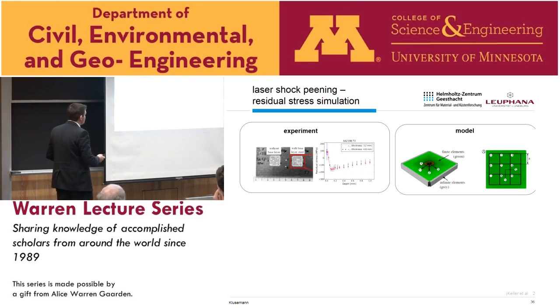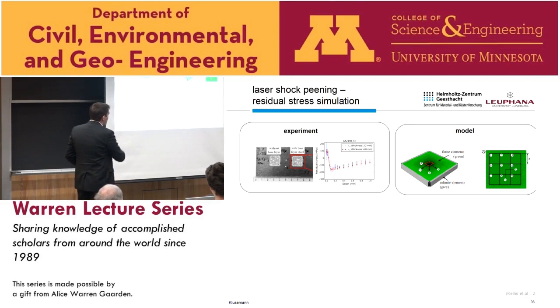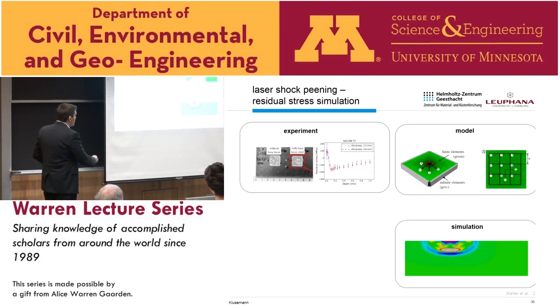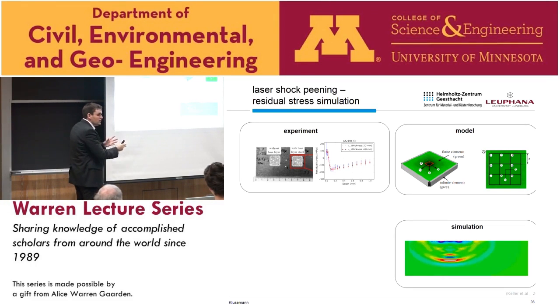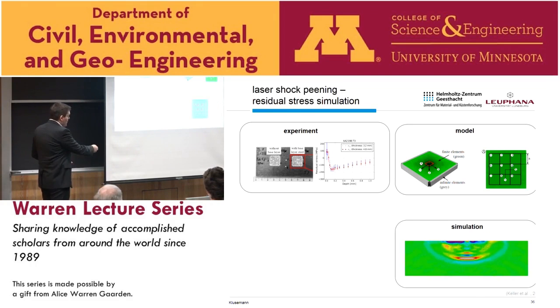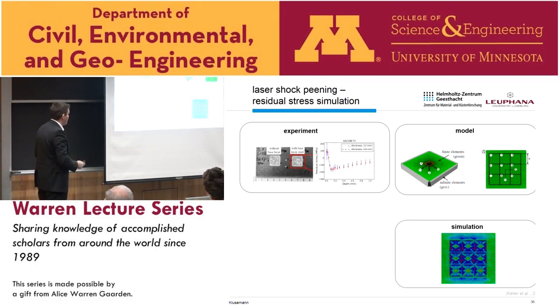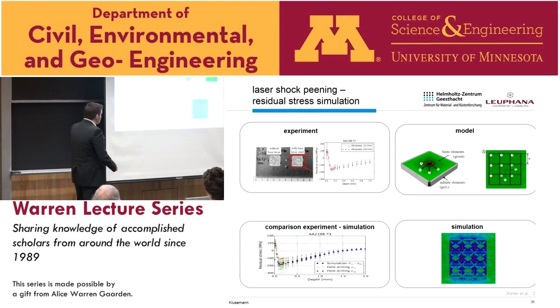We did that for 2198 T3, and this should be the last slide on that. So we have the experiment. We set up our new model now. We incorporated here infinite elements because we know there is no influence of the base layer, so we can account for that. We have our 9-shot model. This is enough for the simulation at this point. Then we could incorporate, of course, how is the influence of each of these shocks inside of a material. So this is how the residual stress profile looks afterwards.